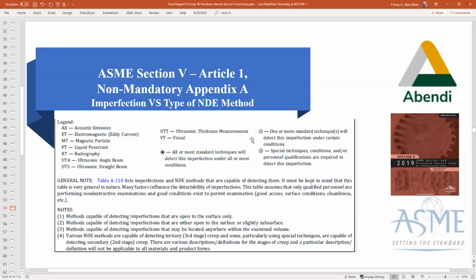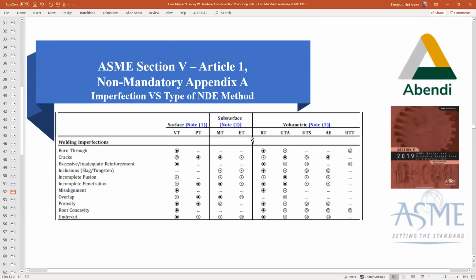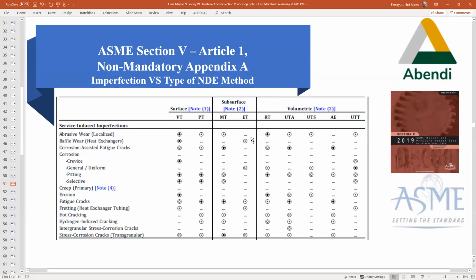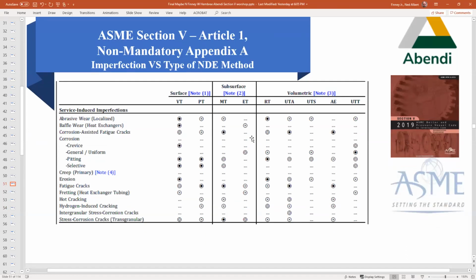So let's go back up to the very first one again. Now we have the legend out of the way. This is contained in the code, directly out of the code, but you can go across the top from surface, VT or PT, and you can see the different types of flaw service-induced imperfections that are identified on the next 3 pages. Subsurface, near surface, mag particle and eddy current, and then volumetric contained within the volume: radiography, ultrasonic angle beam, ultrasonic straight beam, AE acoustic emission, and UT thickness.